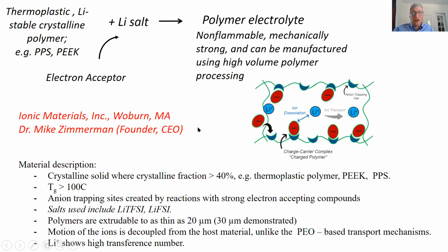My colleagues in Woburn, Massachusetts, just north of Boston, have developed a new polymer electrolyte based on a thermoplastic crystalline polymer, either polyether ether ketone or polyphenylene sulfide. And by adding a strong electron acceptor and lithium salt, they've created a new mechanism where basically you have these defects in the polymer that attract preferentially the anion, which leaves lithium ions relatively free to move. Okay, so there's no attempt to reduce the crystalline phase. We have these anion trapping sites. And these are very easy to process.